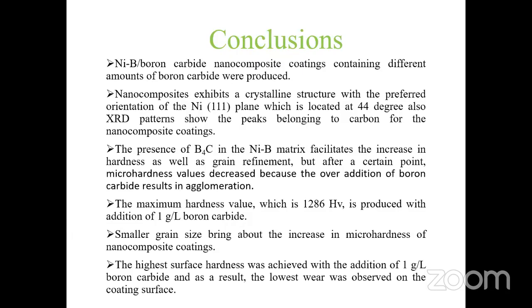The presence of boron carbide in the nickel boron matrix facilitates the increase in hardness as well as grain refinement, but after a certain point, microhardness values decrease because the over addition of boron carbide results in agglomeration. The maximum hardness value, which is 1,286 hardness Vickers, is produced with the addition of 1 gram per liter boron carbide.